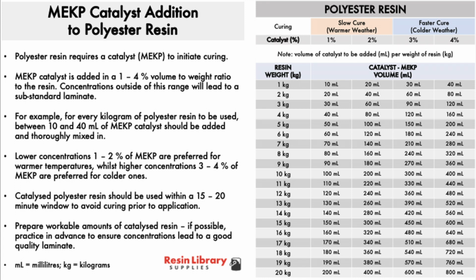Lower concentrations, such as 1 to 2% of MEKP catalyst, are preferred for warmer temperatures, whilst higher concentrations, such as 3 to 4%, are preferred for colder ones.